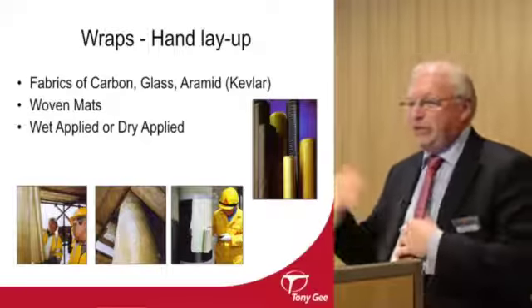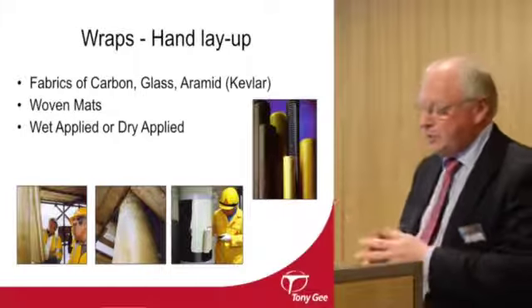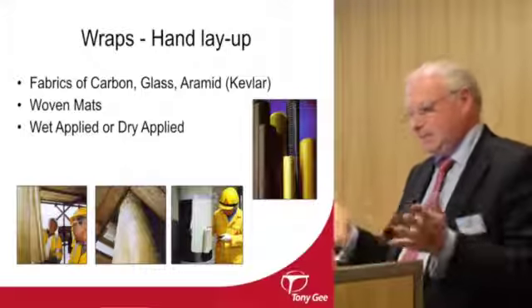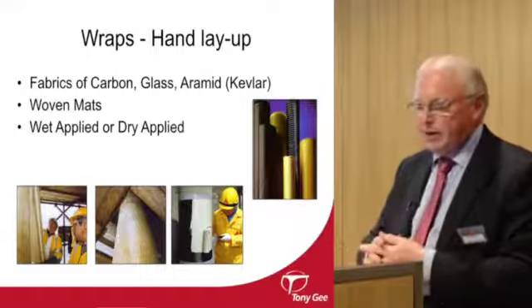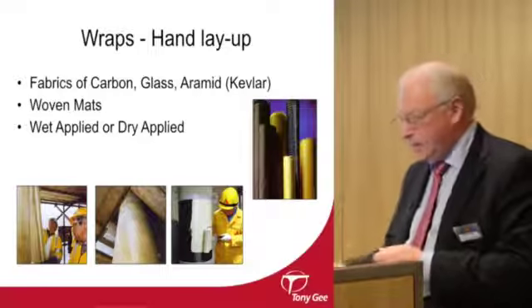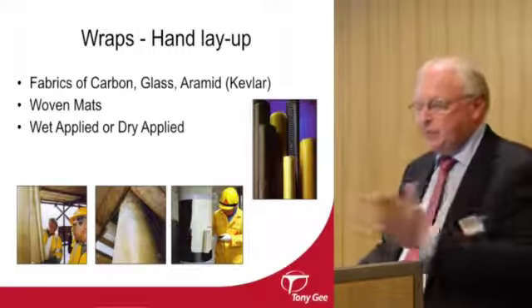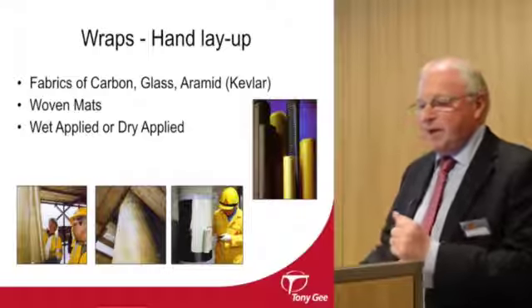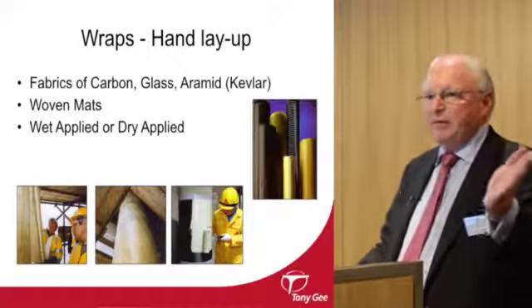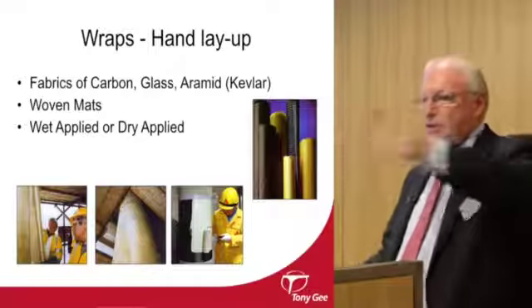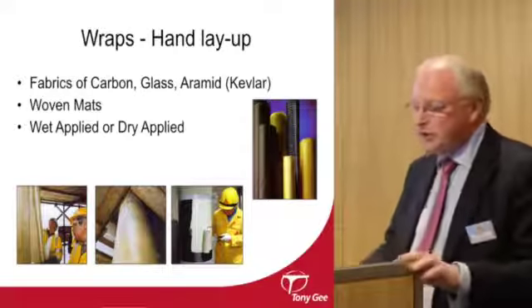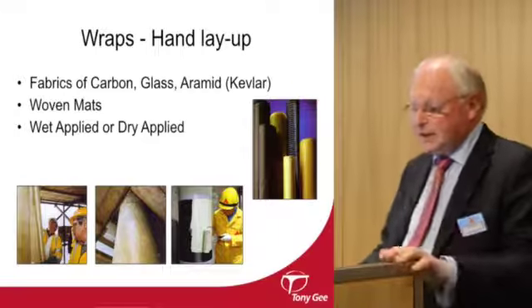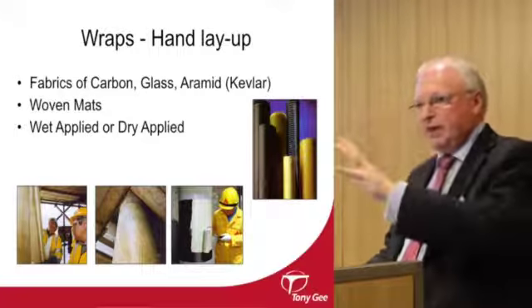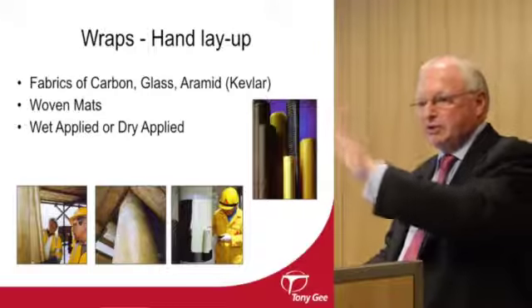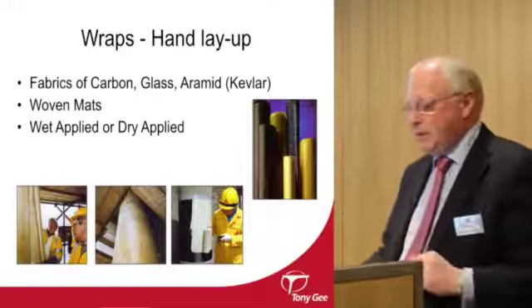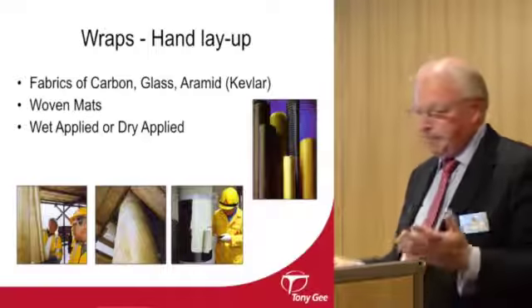Alternatively, you can weave the tows into fabrics. Again, all the three fibres I mentioned can be woven. Then you can take your fabric and use that as your external reinforcement by either dipping the fabric in a bath of resin and then applying it to your concrete structure after suitable surface preparation, or you can apply resin to the structure directly and then apply the dry fabric onto the structure and build it up into layers to the required requirement.